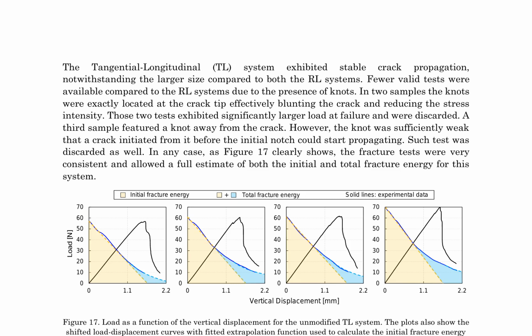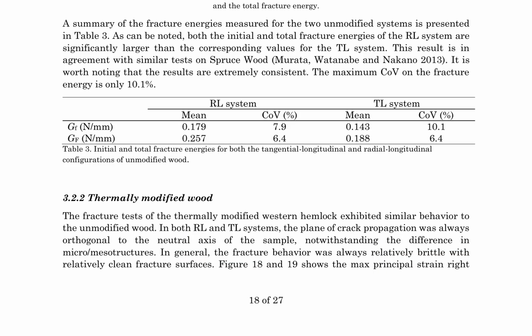Page 18 discusses the fracture tests of thermally modified Western hemlock, which exhibited similar behavior to the unmodified wood. In both the RL and TL systems, the plane of crack propagation was always orthogonal to the neutral axis of the sample, despite differences in mesostructures. The fracture behavior was generally brittle, with relatively clean fracture surfaces. Figures 18 and 19 display the max principal strain right before failure for the thermally modified wood samples, further illustrating the consistency of the fracture tests.